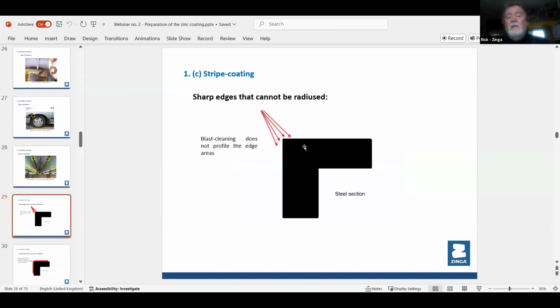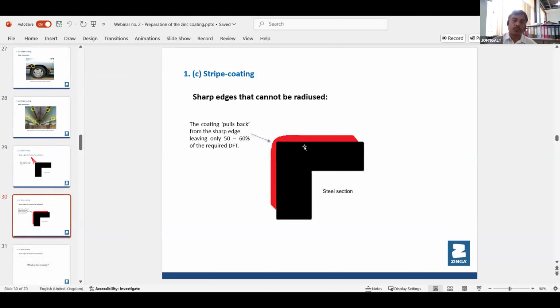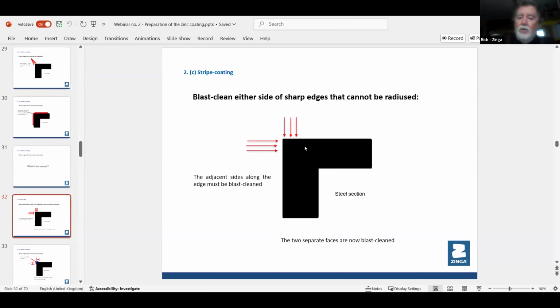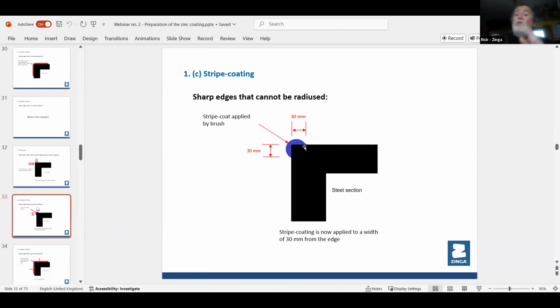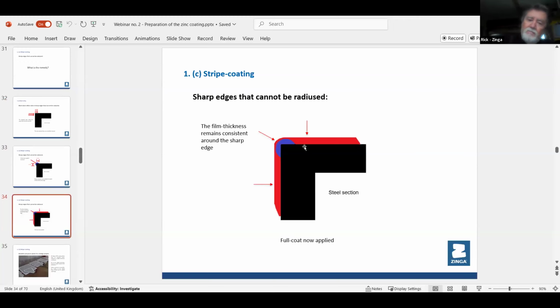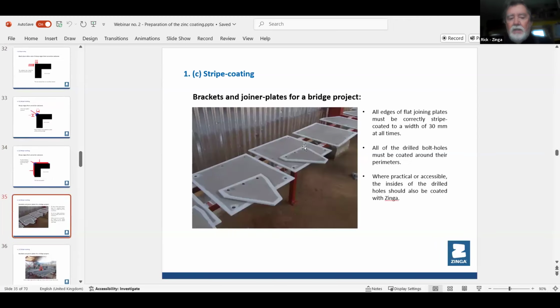And again, the blast cleaning. This is showing you where you cannot radius because it's a bridge or inside a processing plant, and you cannot get access to blast that edge. So we covered this earlier. If you can blast either side of it, and in some cases you might have to grind with a 36 grit sanding disc, but if you can do either side of that sharp edge and then put your stripe coat on, you can still stripe coat it, and that area becomes protected when you put on the full coat. So there's the full coat. So that's fully protected. So stripe coating in every aspect.